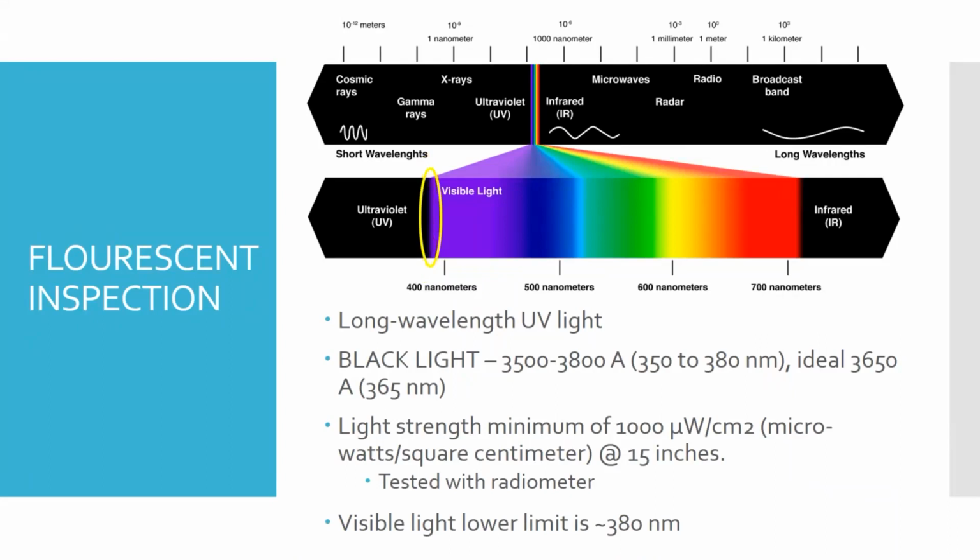Okay. What it means is when we're working with our lights, any one of these UV lights, or these black lights, any kind of a light source never gives out just a single wavelength of light. So the light sources that we have, they have to be able to give out light that is shorter wavelength, more towards the UV spectrum, and longer wavelength. We don't want longer. We don't want visible light. If there's visible light presence, it's going to make it harder to see the fluorescent light, right?